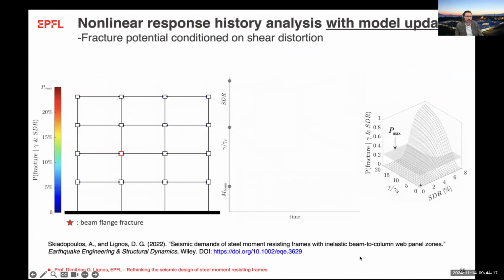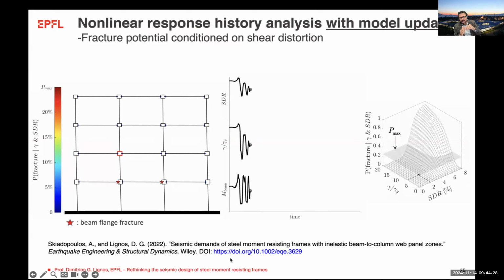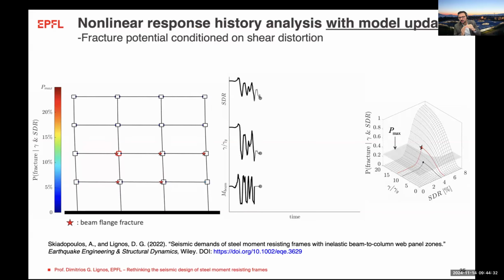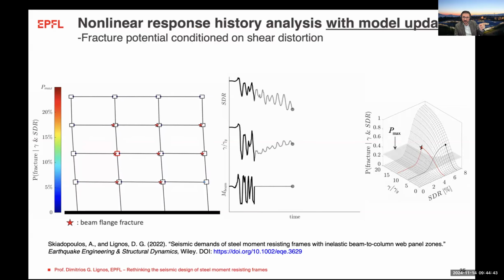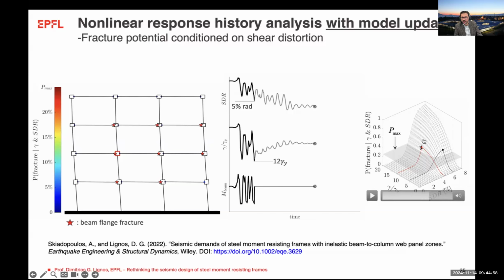And essentially here we are able to run simulations where what we can do is that we are doing model updating so that in case that the panel zone shear distortion reaches a very large value, so that would be 10 gamma Y, what happens is that we are setting the panel zone and the beam strength adjacent to that panel zone to have 0 flexural resistance, as if fracture happens at that beam. And this model updating is informed by this database I showed earlier, where we essentially computed this sort of probability of having fracture in the panel zone given a certain drift and a certain shear distortion.